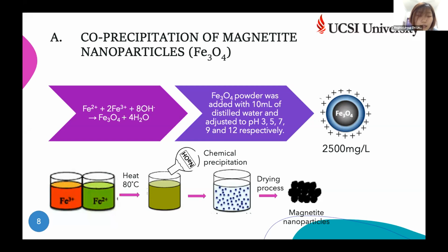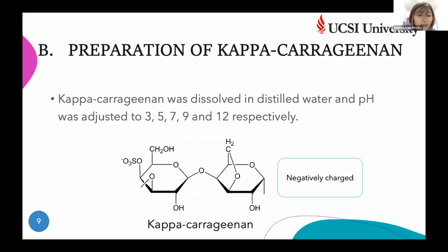Then after drying, the iron oxide powder will be added with distilled water to form 2,500 milligram per liter and adjusted to pH 3, 5, 7, 9, and 12. So in this case, the iron oxide is positively charged. Next, we will prepare the Kappa-carrageenan extracted from Kappaphycus alvarezii and adjusted to pH 3, 5, 7, 9, and 12. So in this case, the Kappa-carrageenan will be negatively charged with sulfate group.